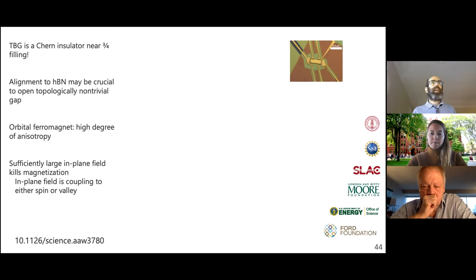I can say in ABC trilayer, I think we can get more insight because in a single sample, we can change the displacement field, change the topological order of the bands, and see that superconductivity and magnetism don't occur in the same conditions. And so maybe we can talk about that more, but in twisted bilayer graphene, I'd probably rely more on the studies where people have looked at the superconductivity and what happens when you have more screening, for example, do you enhance or suppress the superconductivity? If I didn't answer your question, you can type something more, Rick.